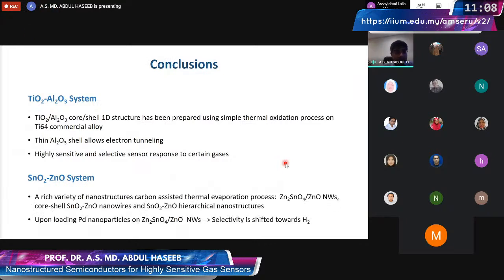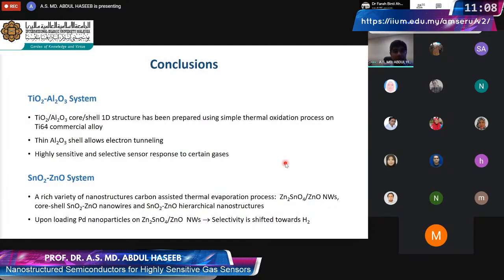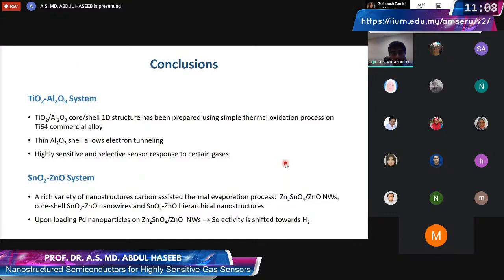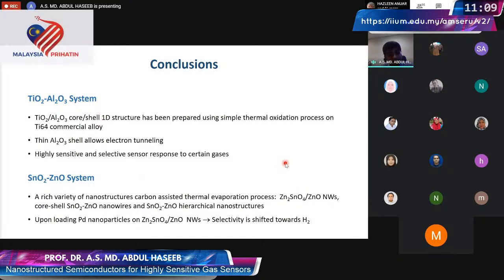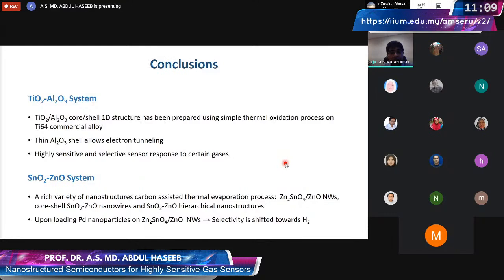We also have seen that the zinc oxide, tin oxide system is very interesting in the carbothermal reduction process. It can allow us to create a lot of different morphologies by changing different parameters. And we have found out that zinc tin mixed oxides are sensitive to certain gases, and we can even change their selectivity by doping them with different nanostructure materials. So with that, I have to thank you all very much, the audience, for being with us,